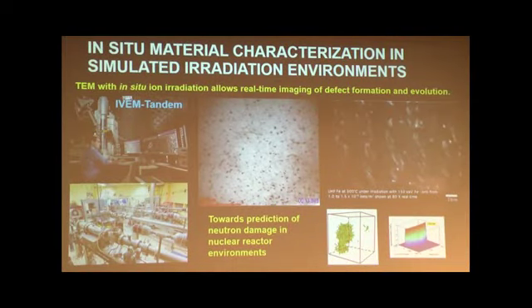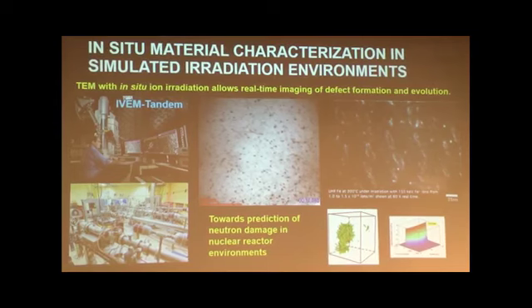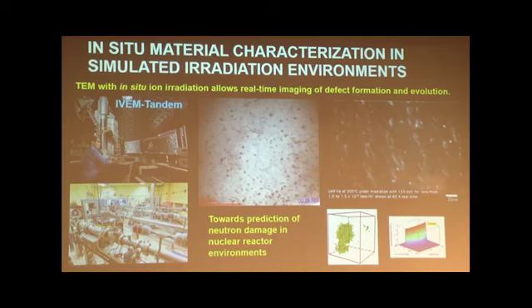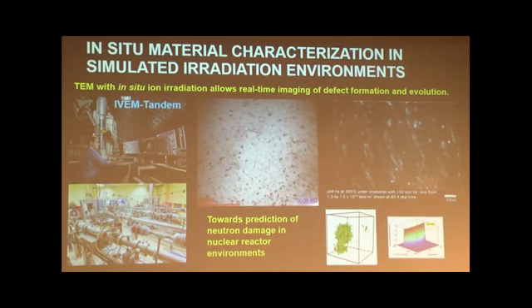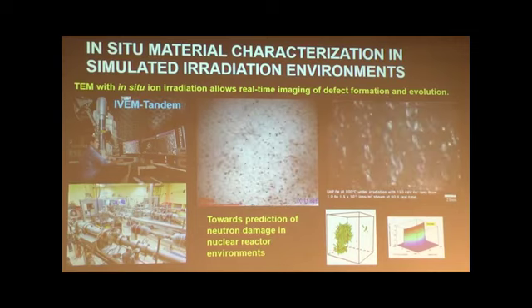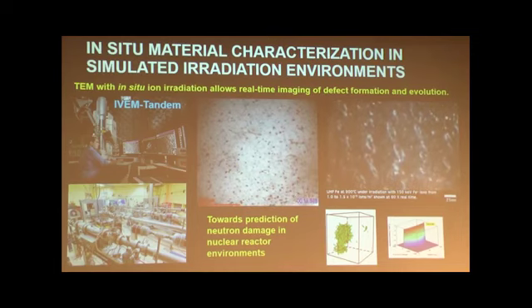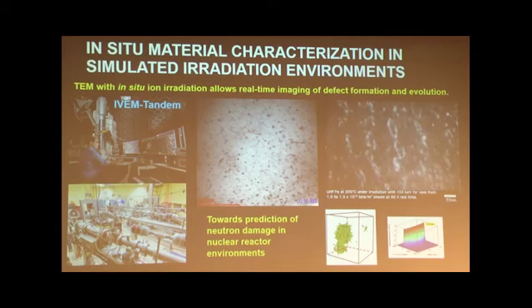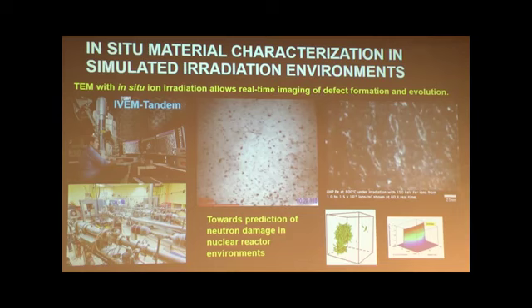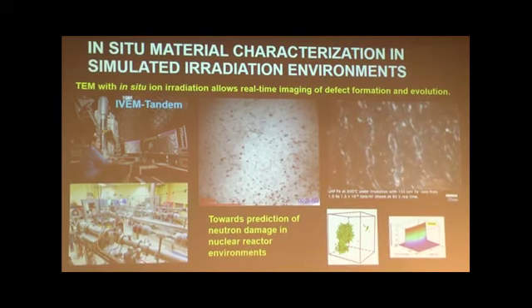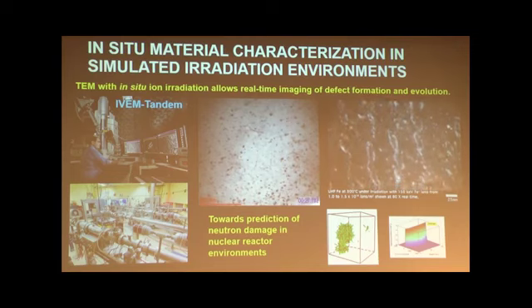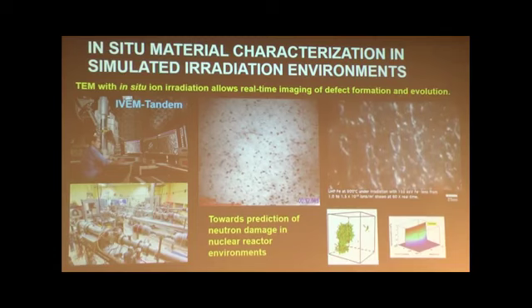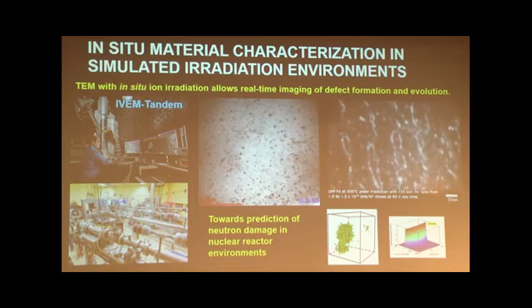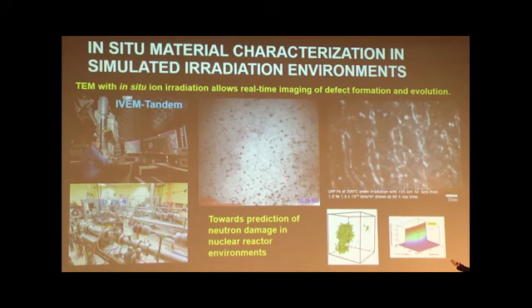So in the previous examples, when I talked about in situ experiments, you probably noticed there's one environmental factor missing, which is radiation. We know once we put material in the reactor, the damage will happen in a picosecond or even shorter time. So being able to see how radiation damages material, generating defects, is very important. At Argonne, we have a facility called IVEM-Tandem. Basically, this is a TEM that's interfaced with an ion accelerator. So we can use heavy ions to generate radiation damage that's similar to neutron damage, and we can watch how defects are generated and evolved.